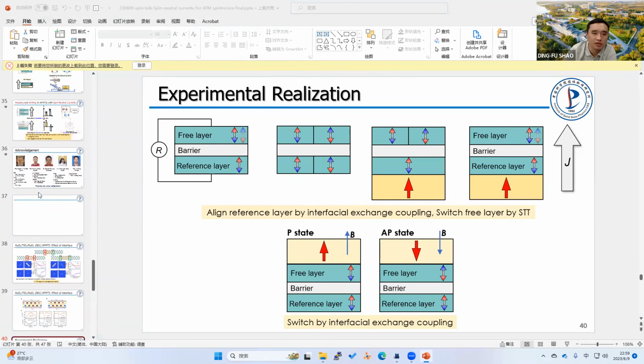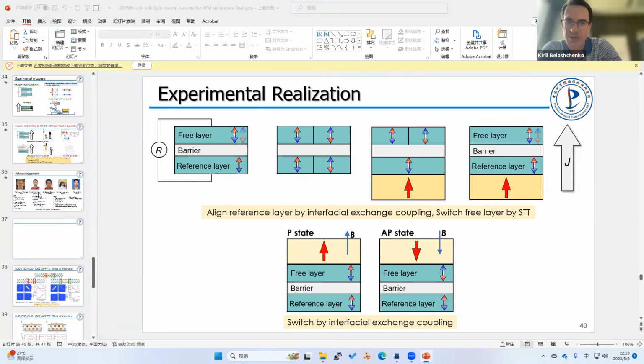So in fact, remember, there were some studies quite a while ago for conventional antiferromagnets, and it was found that you can have TMR and torques for particular collinear magnetic ordering, but if you have roughness, those tend to be destroyed. So I think this will be a concern here if the roughness tends to place different magnetic sublattices randomly against each other on the two sides of the barrier. You showed some cases where that doesn't seem to be the case, so maybe you can comment on that some more.